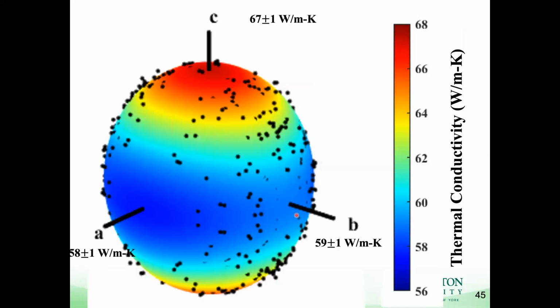So next we took each one of those measured thermal conductivity grains and plotted it on this 3D plot. Each one of these points represents a grain, and the distance from this point to the origin is the magnitude of thermal conductivity, and the orientation from the origin is basically the normal surface for that grain in the ABC coordinates. So we could see that the thermal conductivity in the C direction was the largest, and in the A and B directions, they were quite similar, about 58 or 59 watts per meter Kelvin.